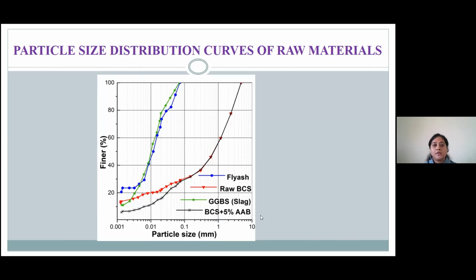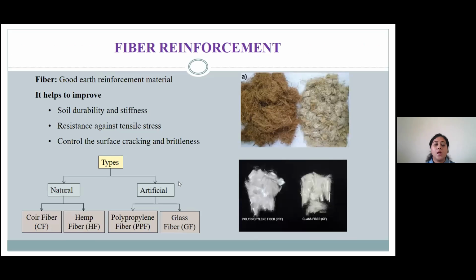We have used 5% of AB. Rather, we have tested from 2 to 10% of AB, and then found out that 5% AB is the optimum content. So we have presented here the graph of 5% AB.